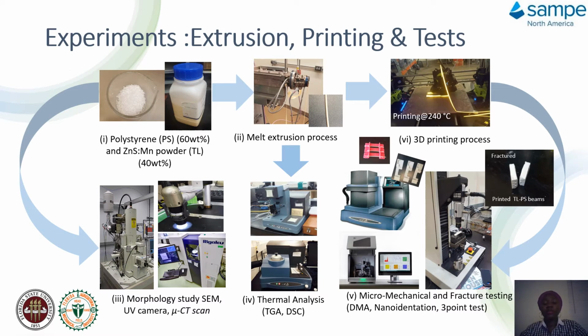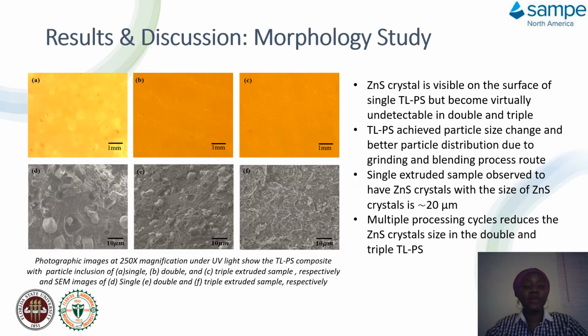And DSC shows the glass transition temperature or the melting temperature for the material, in order for us to know the temperature to set when printing with the filament from the printer. And after that, we print out a beam to be able to test for 3-point bending, fracture test, and also later on we check the mechanical properties using nano indentation as well as the DMA, which is dynamic mechanical analysis.